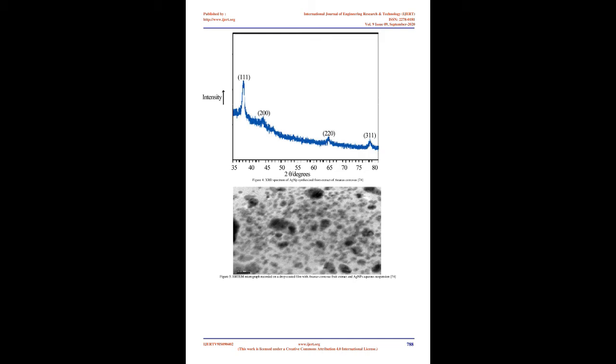Depending on the conditions, silver ions may favor either the process of nucleation or aggregation to form nanoparticles. Silver nitrate, silver acetate, silver citrate, and silver chlorate are usually used as silver source. Numerous researchers have synthesized silver nanoparticles using the chemical reduction approach. For example, Zahir et al. 64 have prepared AgNPs by reduction of AgNO3 solution with aniline in presence of CTAB.